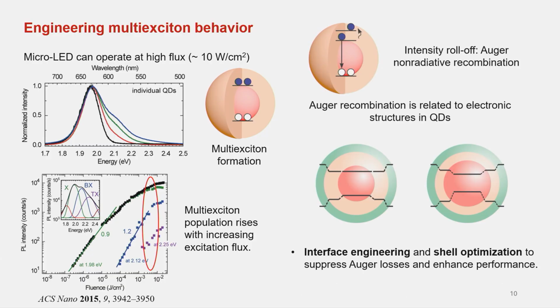Another effect from the multi-exciton is Auger recombination. In this case, instead of emitting a photon, it excites another exciton into a higher energy level, which doesn't give you light. So Auger recombination is also considered one of the major reasons for the intensity roll-off in normal quantum dot LEDs as well.